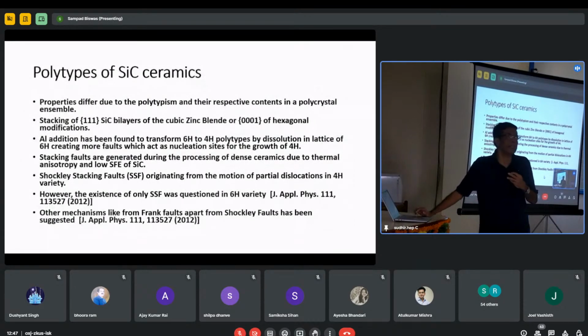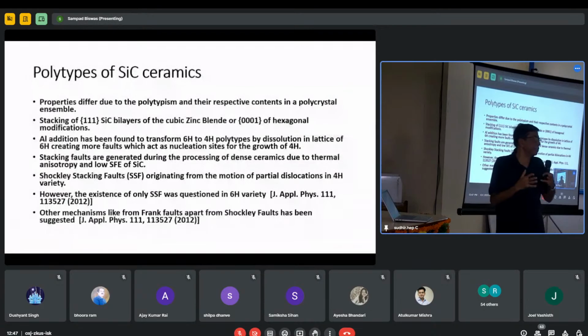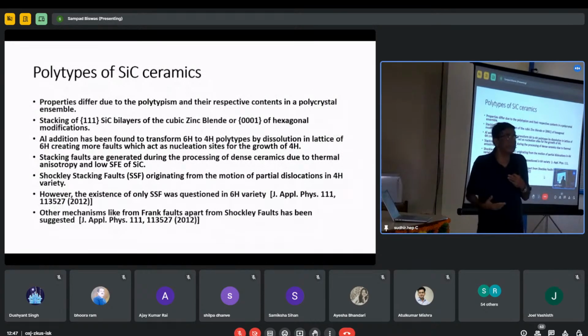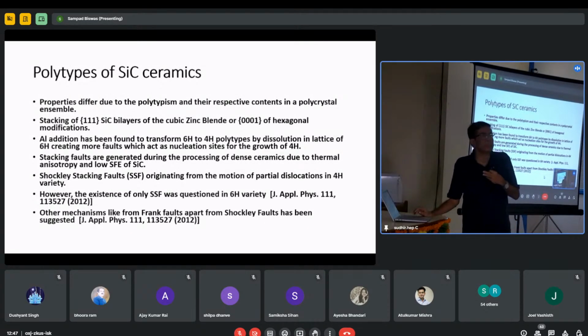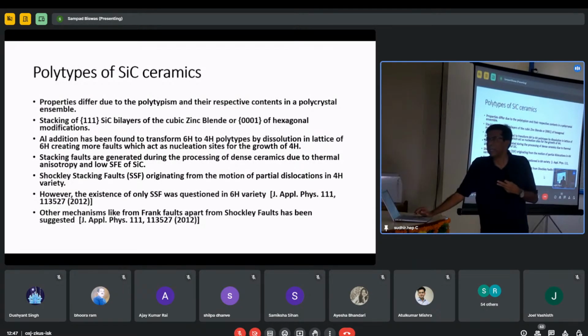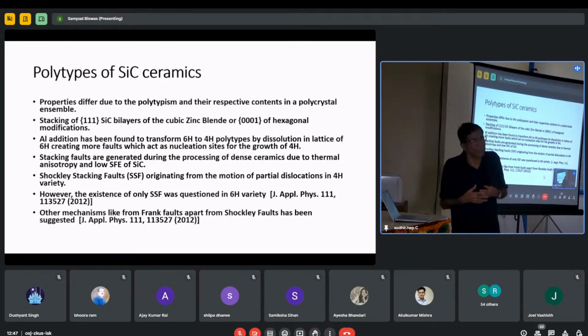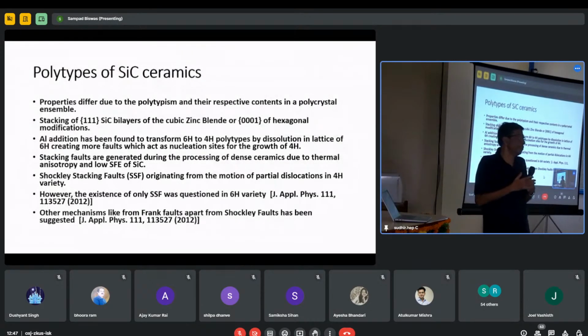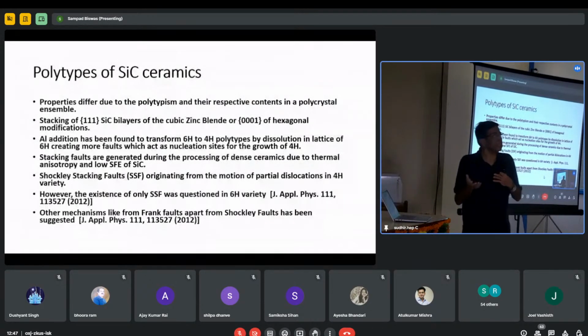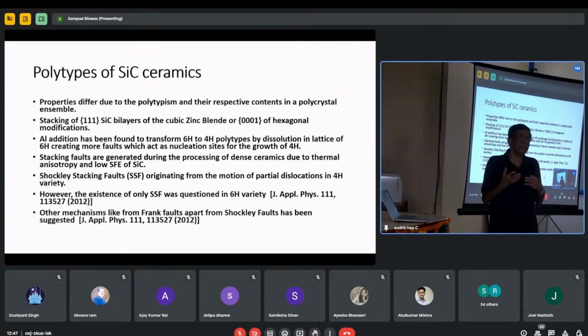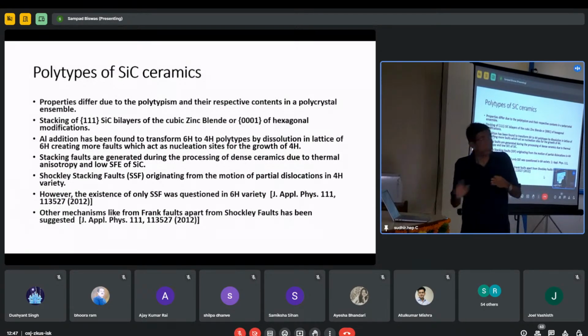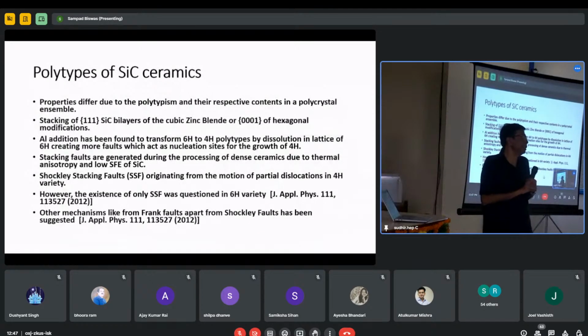It has been found that during processing, you have to add some aluminum or boron or carbon within the material to get it densified to a maximum density, say about 98%, 99% relative density. And you have to add some metal ions like aluminum. What happens? This aluminum goes into the 6H structure, and it converts it to the 4H structure. It creates faults within the lattice, and it then converts it to the 4H structure. So this polytypic transformation is very important in these silicon carbide ceramics.